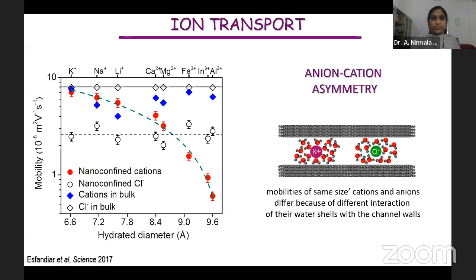But when the channels become really thinner, twice thinner, even K plus cannot move through those channels. But to be honest, it's all cartoon. This requires a better quantitative explanation. Even molecular dynamics simulations are not very good for this kind of atomic scale physics, all I can say.